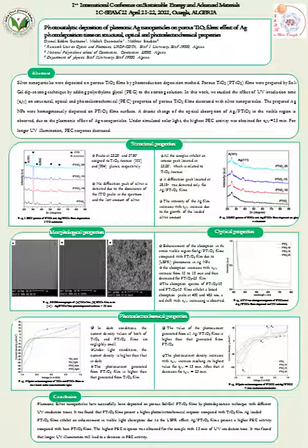To confirm the presence of the silver, XRD patterns of films deposited on glass substrates are presented in Figure 2. Beside the peak of anatase, we note the presence of a peak assigned to silver, and the intensity of this peak increased with UV irradiation time increase due to the growth of silver amount.